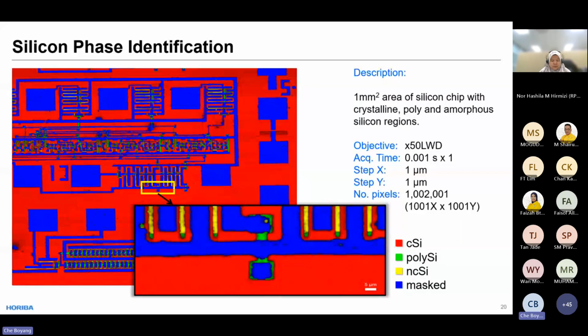So the first example here is on the semiconductor. This sample is a silicon wafer, and we use the Raman to map a very large area of this piece of silicon. Because it may contain crystal or amorphous silicon, and the crystallinity will also show difference in the Raman spectrum, we are able to use the Raman to differentiate between the crystal and the amorphous silicon. If you zoom in on this area here, we can find 3 types of silicon. The red color is crystal silicon, green color is polycrystalline silicon, and yellow color is amorphous silicon.